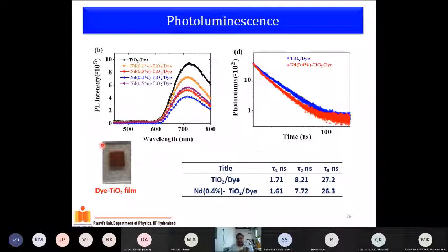So you should have an emission corresponding to the 100 photons, which is a strong emission. Now when you put this dye onto titania, the dye injects its electrons. Let's say the electron injection is fantastic, 90% injection, 95% injection. What does it imply? Out of 100, 95 electrons have gone into the titania. So only 5 electrons are left on the excited state of the dye to relax down.